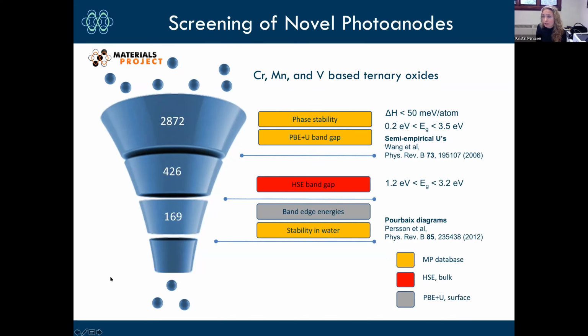So now we calculate surface properties, so band edge energies, and we also screen on stability in water, criterion number 3. And we get the magic number of 47. 47 materials that we thought were reasonably good ideas for John Gregoire to try to synthesize and look at from his perspective in terms of photocatalytic activity for oxygen evolution.